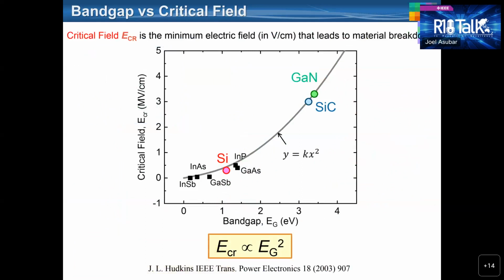Well, the higher the band gap, the higher the critical field. And critical field is the minimum electric field that leads to material breakdown. It was shown by Hudkins that the critical field varies parabolically, or as the square of the band gap energy, which means that the higher the band gap, the more robust or stronger the material is against the applied voltage.